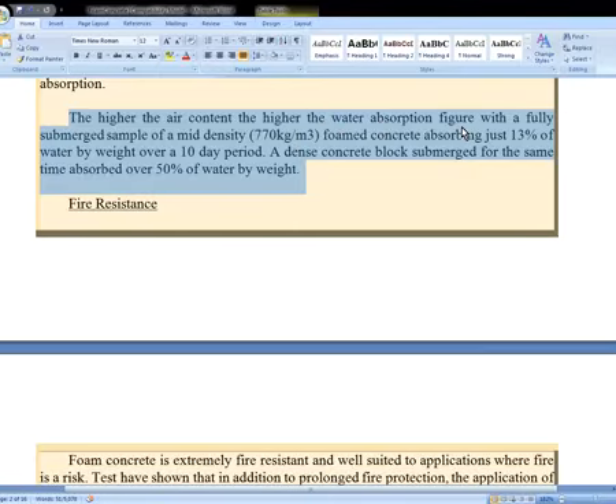higher water absorption figure. With a higher air content there is a higher water absorption figure. With a fully submerged sample of a mid density, 770 kg per meter cube foam concrete absorbing just 13%. 770 kg will absorb just 13% of water by weight over a 10 day period. It takes this much water in 10 days. A dense concrete block submerged for the same time absorbed over 50% of water by weight. This means ordinary concrete will be 50% in 10 days, and this will be 13%. This means it's about one fourth. It takes in 10 days 25% absorption in comparison to ordinary concrete.